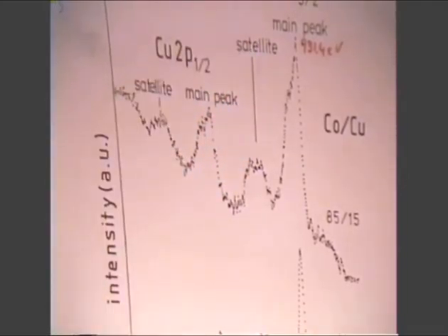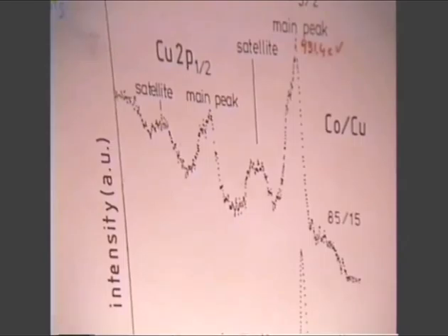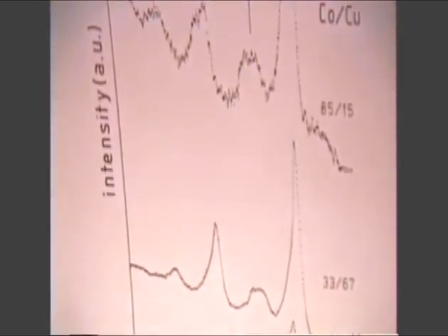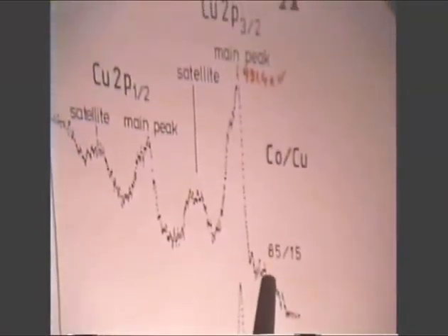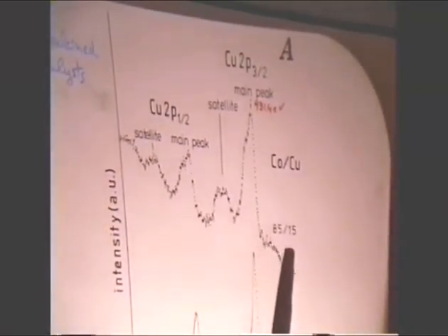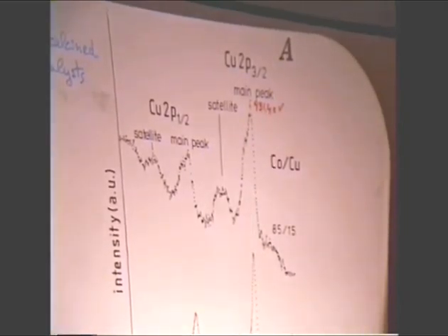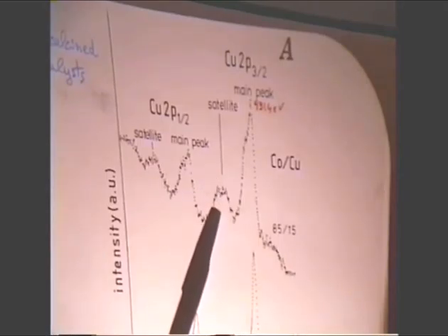The XPS spectra of the cobalt copper mixed oxide catalyst were characterized by an asymmetric main peak, prefiguring the existence of two components, one related to copper 2 plus ions and the other related to copper 1 plus ions. In fact, the binding energy of the main peak of the catalyst with a cobalt copper composition of 85-15 is much closer to the copper 1 plus species, and also the satellite peak is not as intense as for the pure copper oxide.